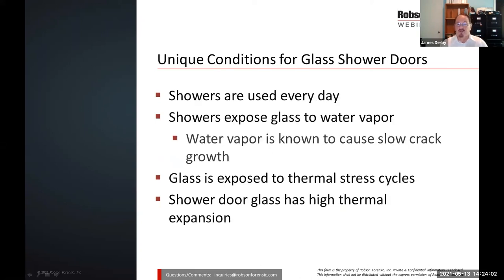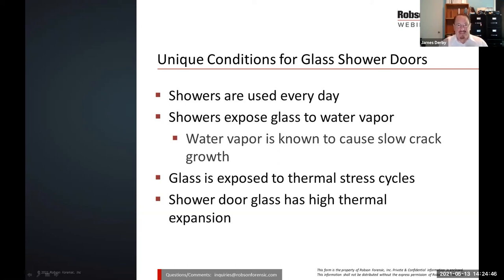Some unique conditions for glass in shower doors: showers are used every day, probably multiple times a day, exposing the glass to water vapor, which is known to cause slow crack growth. Glass is also exposed to thermal stress cycles every shower — the shower might be 120 degrees, then you turn off the water and the temperature of the door drops to 70, then the next shower brings it back up. This glass is high thermal expansion glass, and these thermal cycles produce thermal stress within the material.